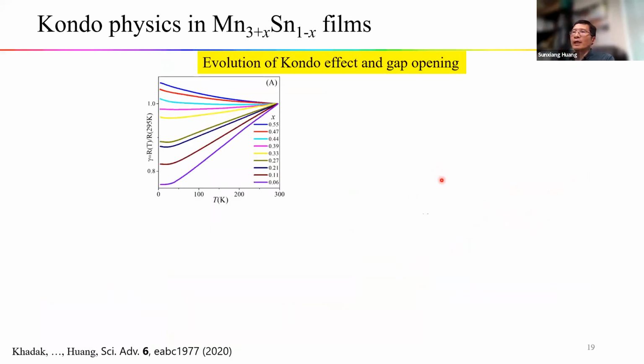Okay, so now let's look at what happens when we have the extended magnetic doping in these same films. From the low doping to the high doping, the resistance versus temperature curve shows different behaviors. For low doping, it has metallic behavior with some residual resistance. For the high doping, we actually see semiconducting or insulating behavior.